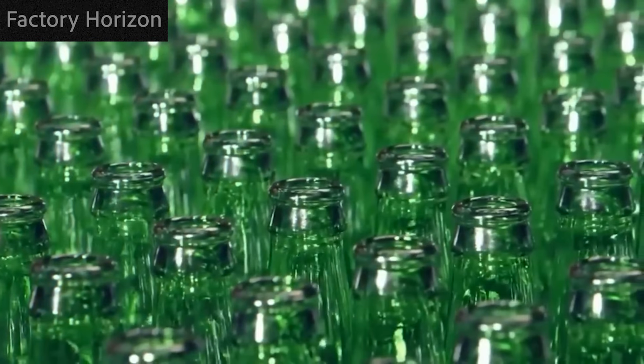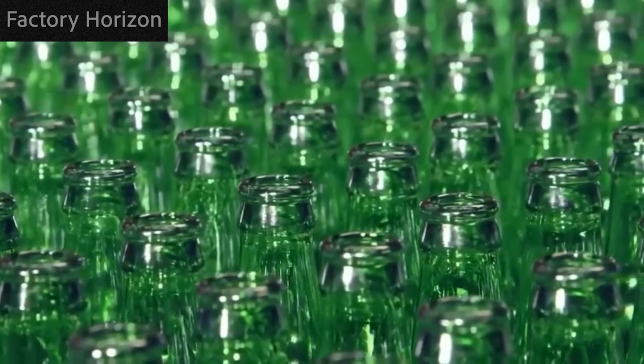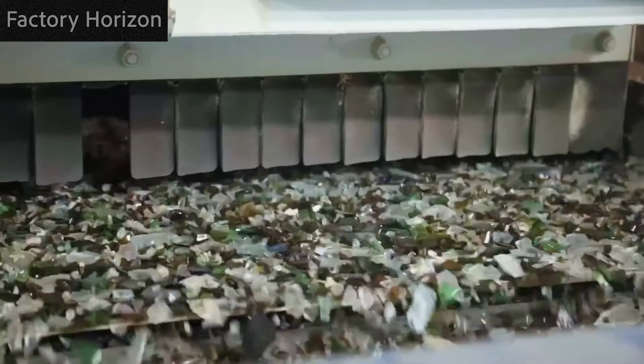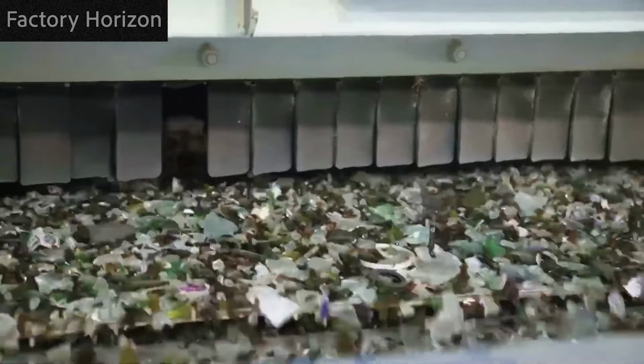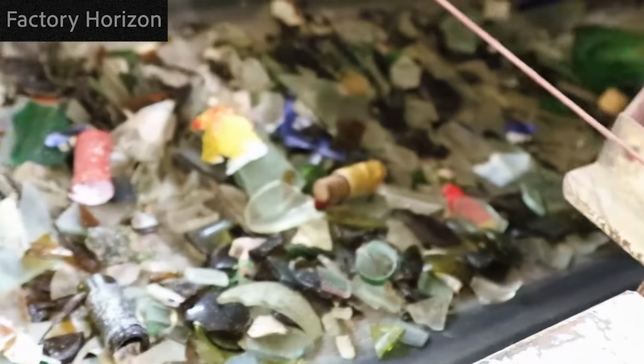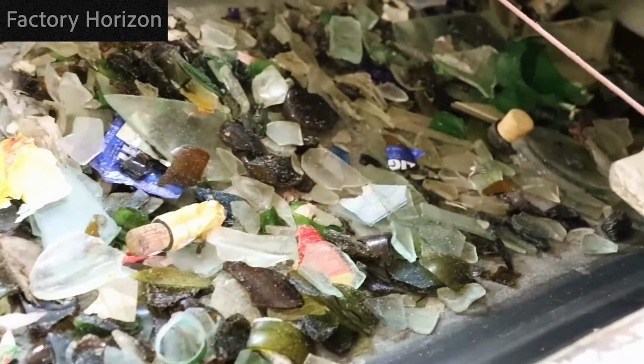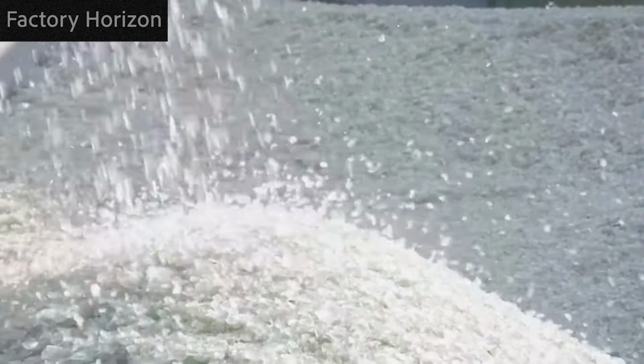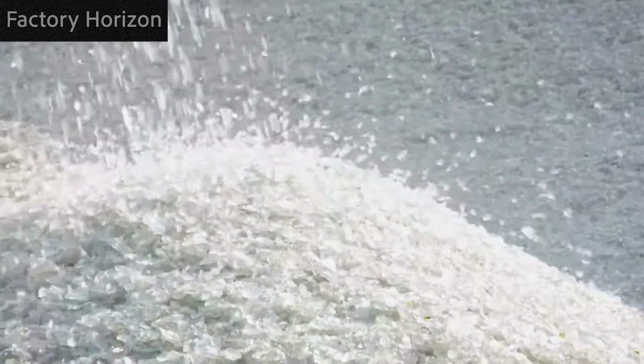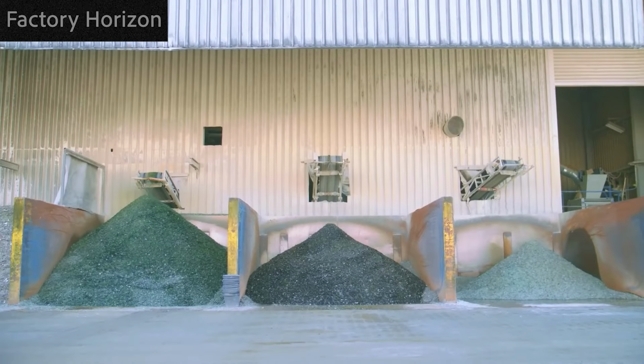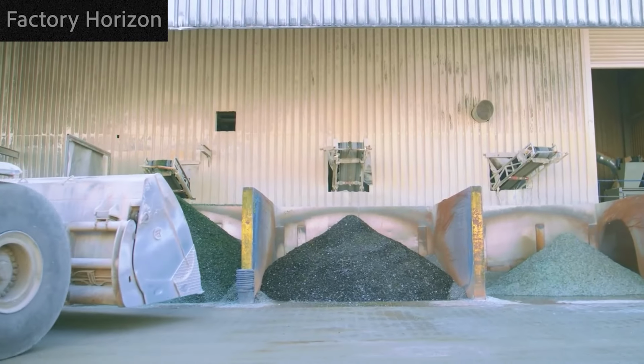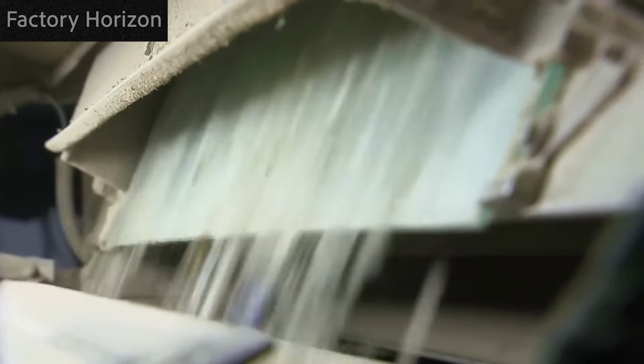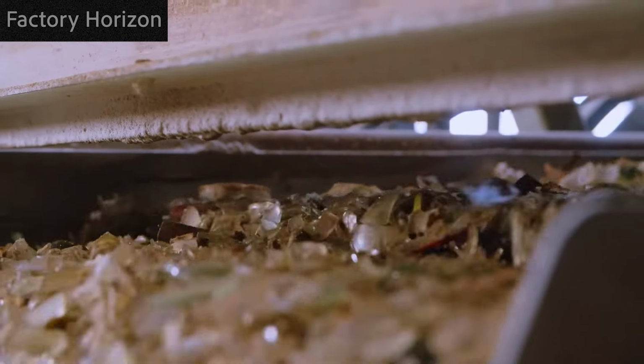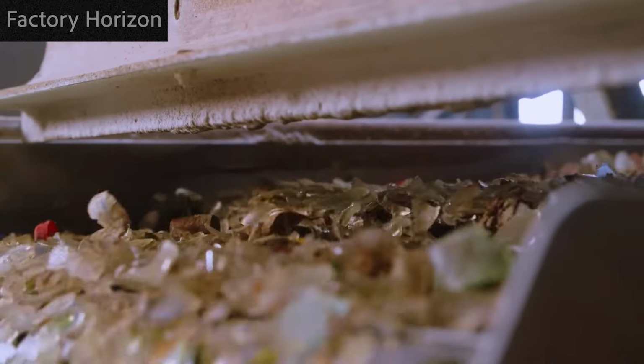The crusher roars like a mechanical beast as the first clean bottles drop into its steel jaws from an overhead hopper. Hardened steel hammers spinning at 900 revolutions per minute pulverize glass into fragments smaller than your thumbnail in violent impacts. The machine devours 20 tons of whole glass every single hour, reducing sturdy bottles into a granular material called cullet. That's the official industry term for crushed recycled glass that's ready for melting.